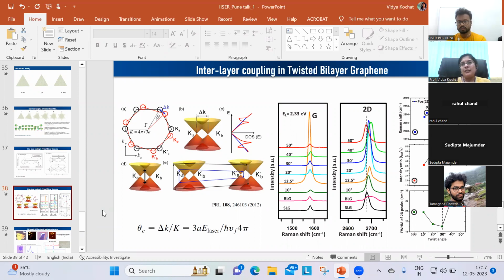But for other samples, you have to calculate the surface energies for HBN and for the other 2D material that you're trying to pick using HBN. So it will depend upon how the adhesion energies are different for these two systems. If there is a very good adhesion energy, then you can easily pick it up using HBN. So HBN is preferred because it has adhesion energies which are very close to graphene and TMDs.